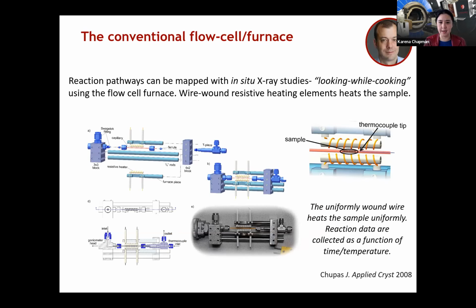This is an in situ reactor that I think maybe quite a few people will have used, where we can heat the sample under controlled gas flow. We have a thermocouple right next to the sample giving feedback of the temperature, and a wire-wound heater heating the sample. This allows us to look at a lot of reactions, but of course we can only look at one temperature at a time.